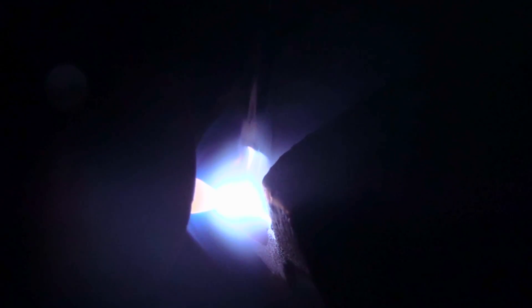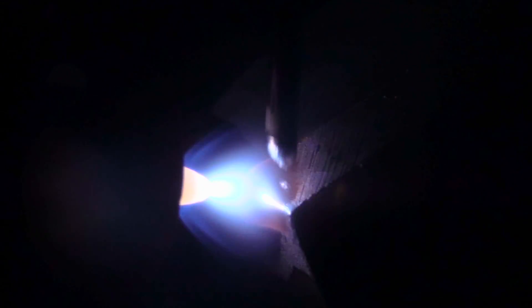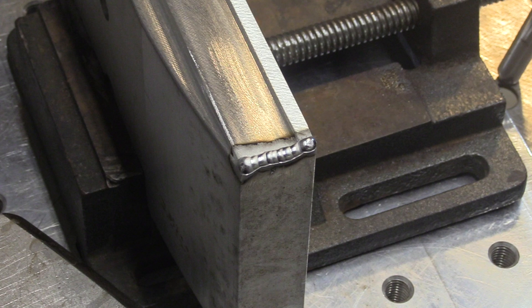And then it should, it's wetting out and welding fairly clean. Doesn't look like there's any porosity in that. Or if there is, it'll be very minimal. If it doesn't puddle cleanly, I back off the pedal and just let the cleaning action work until it does puddle cleanly.